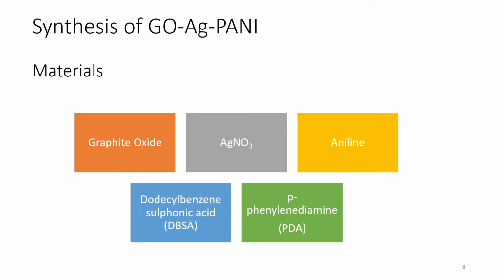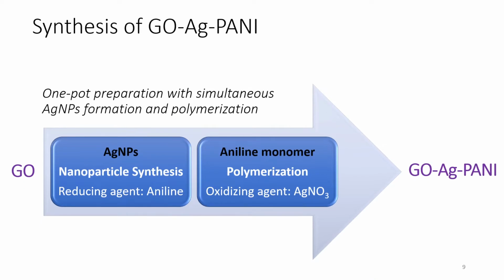The materials we used for the synthesis process were graphite oxide, silver nitrate, aniline, dodecylbenzene sulfonic acid for acidic medium for polymerization, and phenylenediamine for increasing the rate of polymerization process. And the synthesis method is a one-pot preparation with simultaneous formation of silver nanoparticles and polymerization. Silver nitrate is oxidizing the aniline monomer, and silver nanoparticles in turn are reduced by aniline polymerization.